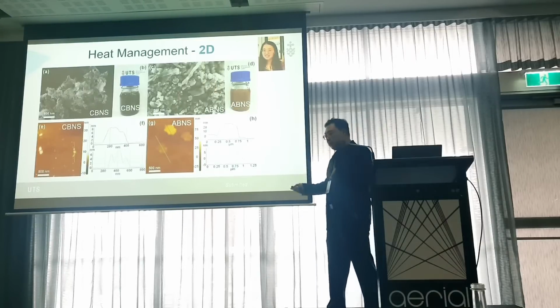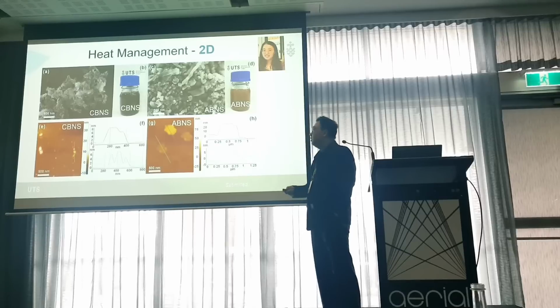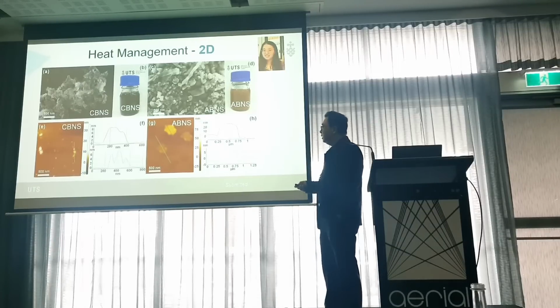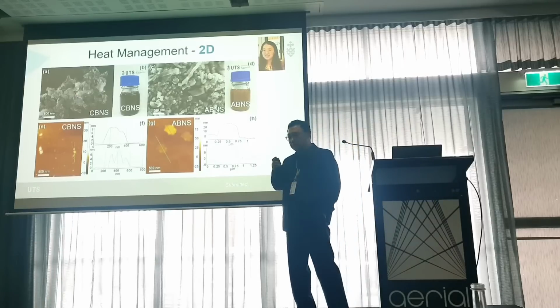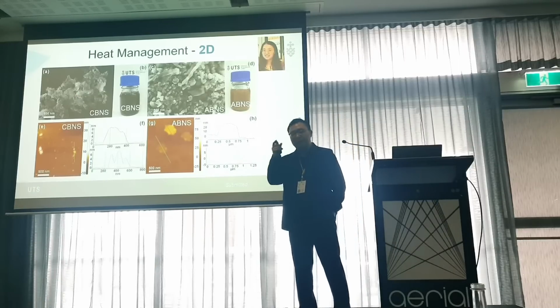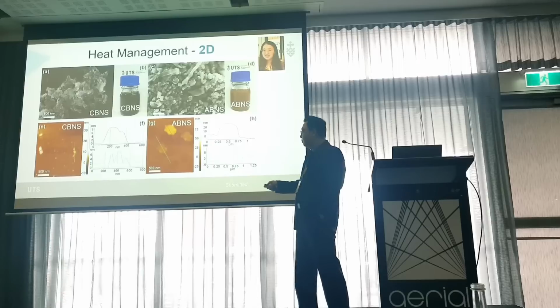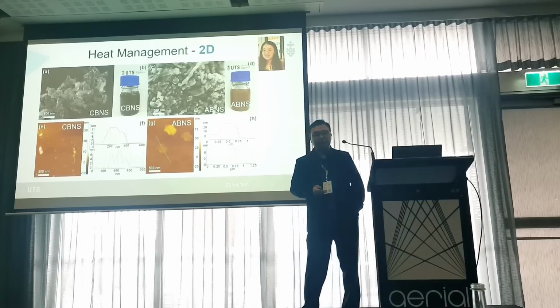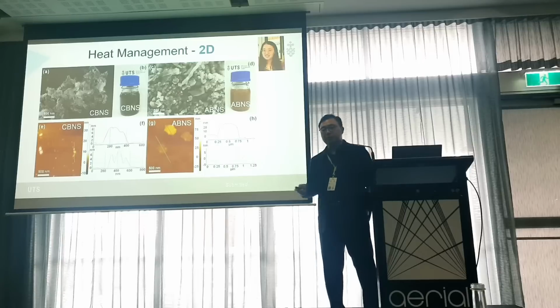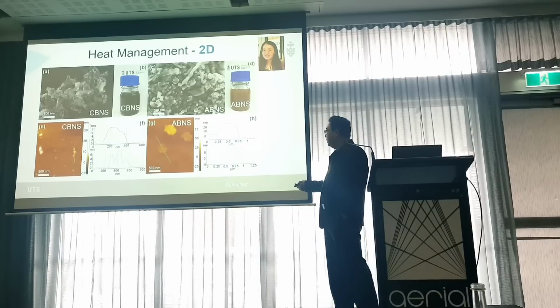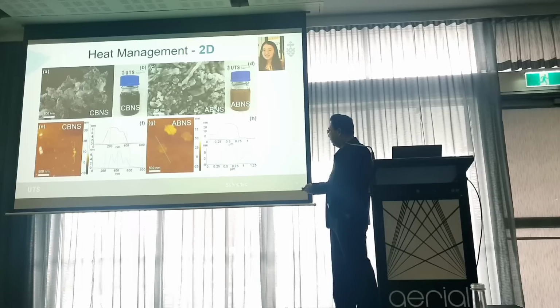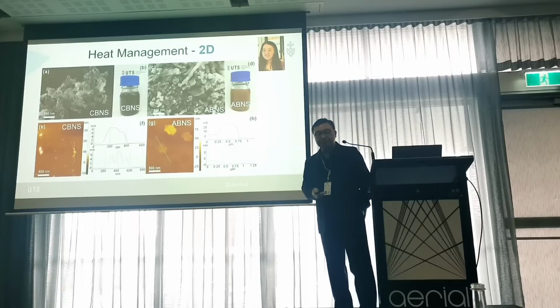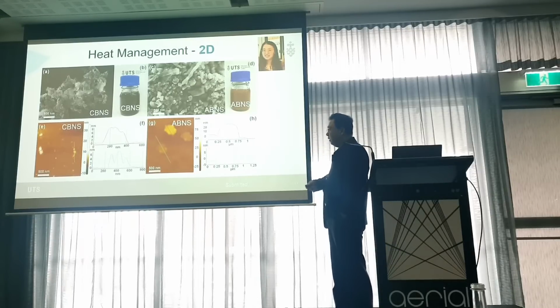And then we wash these materials and disperse them in water and characterize them by SEM, and as you can see, the crystalline boron nitride nanosheet is relatively smaller and has a higher aspect ratio. The thickness is about 7 nanometers, while the diameter is about 300 nanometers. In contrast, the amorphous boron nitride nanosheet has a greater thickness, about 20 to 30 nanometers, while the diameter is about 500 nanometers. So the crystalline boron nitride nanosheet has a higher aspect ratio.